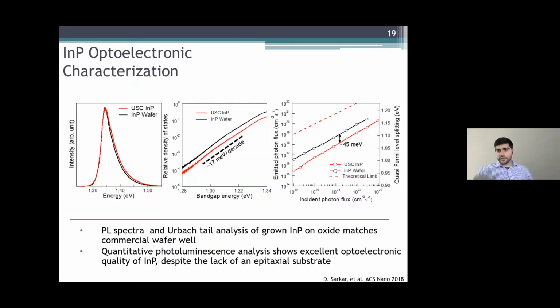When we grow these materials, for indium phosphide we would do optoelectronic characterization. And one of the things that we're showing here is the indium phosphide, which we would grow on top of oxides and nitrides, half a micron to 3 micron thick, versus a similarly doped crystalline indium phosphide wafer. And what we're doing is we're just comparing photoluminescence characteristics. So we're comparing our peak position, our full width half maximum.